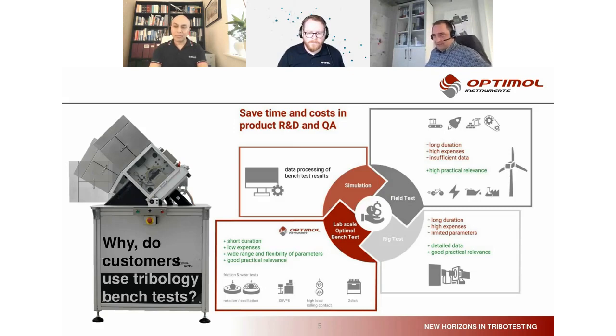The benefit of the lab scale testing compared to those field and rig tests is you have a short duration, you have relatively low expenses for one test, and you have a wide flexibility of parameters with a good practical relevance if you don't do only model tests. So the trick in this case is you have always to try to bring the real stress collective into the tribo tester. And this is our expertise at Optimol.